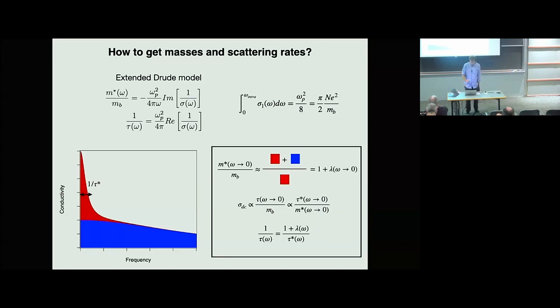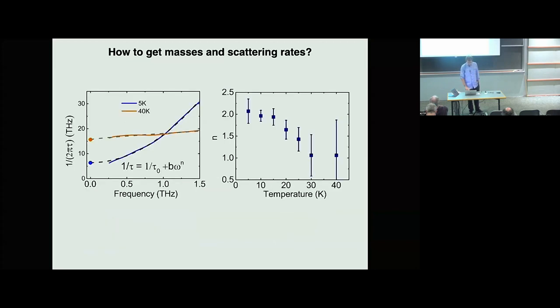Okay, I'm out of time, so let me just show you that. These are different definitions for 1 over tau, 1 over tau star, and M star. Very often in the optics literature, people concern themselves with 1 over tau. And there it is from our data: at 40 Kelvin, essentially independent of frequency, maybe with a slight slope; at 5K, deep into the heavy fermion state, 1 over tau as a function of frequency has this kind of curved form, and that dashed line is a fit to an exponent n equals 2. We like to do this fit as a function of temperature. You can see that at low temperatures, it's quite consistent with 2, which is what you would expect from a Fermi liquid. So it goes like omega squared, good.